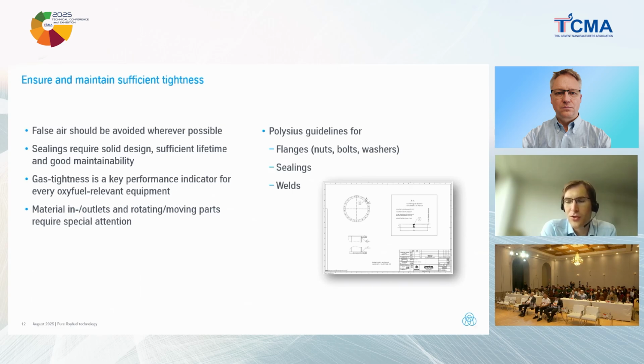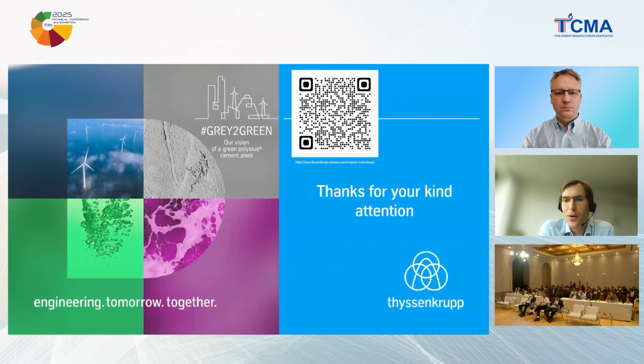False air before the combustion is already a nuisance, but at least oxygen from the false air can then take part in the combustion and is converted to CO2. But false air downstream of the calciner is even more critical because it not just lowers the CO2 purity, but also increases the oxygen concentration. So this is a first overview of the Catch for Climate project regarding the kiln line technology. Thank you very much for your attention.